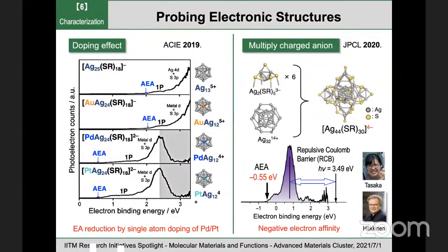And by using this method, we can probe the intrinsic electronic structures of the superatoms in the absence of the solvents and the counter anion. The left panel shows that the electron affinity of silver superatoms can be reduced dramatically by doping a single palladium or platinum atom at the center. On the right, multiply charged silver superatoms do not lose the electron in the gas phase, although the electron affinity is negative. And this is due to the electron being confined in the superatomic core by the repulsive Coulomb barrier created by a negatively charged surface unit.